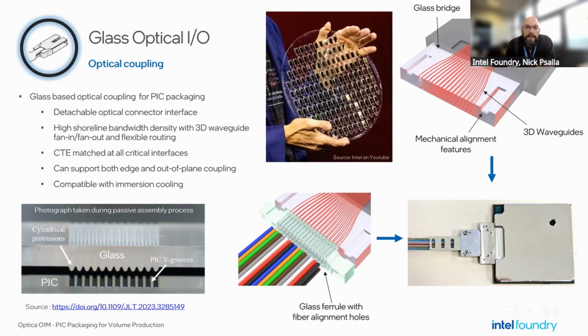You can see some examples here of some actual parts. The lower left-hand image shows a bridge that contains passive alignment features. In this case, these are cylindrical protrusions, which are designed to mate directly into an existing PIC that has V-grooves in it. In the middle, you can see an example of a reconstituted wafer that's used for wafer-level assembly and test on a carrier wafer. And on the lower right-hand side, you can see a fully packaged example which has the bridge and the connector all integrated in, with all the relevant mating mechanics to make that work.